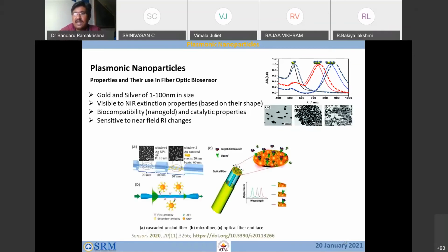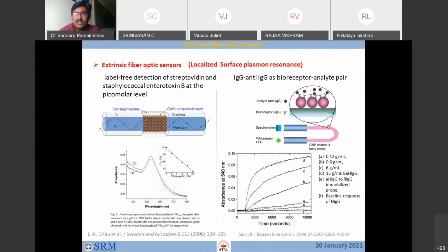People have tried lab on tape and lab around fiber, and multiple fiber technologies have come. Now this is another technology where the fiber is coated with nanoparticles that are sensitive to environmental change. People tried this and got very good sensitivities for the biosensor. However, the sensitivities are still not attomolar here. They are in the nanomolar and micromolar range only. So in order to improve the sensitivity, people tried a U-bend structure, enhancing the evanescent field or the light interaction with the nanoparticle, and then they got very good sensitivity, at least 10 times better than the straight fiber. Here it is the intrinsic properties, or it is simply refractive index sensitive.